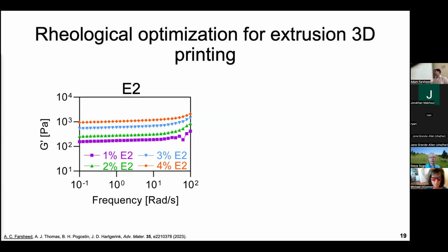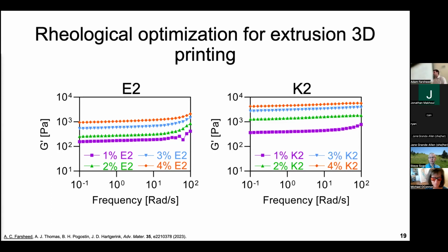And so if we run this same sort of experiment with K2, we see that we're able to achieve gels that are much stronger than what we had previously seen in our lab by going up to this 4 weight percent concentration. And so I got very interested in this 4 weight percent concentration because when I was working with this material, I was like, this is able to hold its structure itself. Can we validate that this material is going to be useful for 3D printing and meet some other things that are necessary for what it takes to be 3D printable?